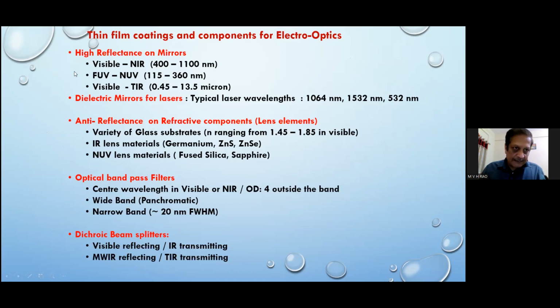A variety of optical films are made: high reflectance coatings on mirrors, and dielectric mirrors for lasers, for different types, 1064, 1532. These are lasers. Anti-reflection coatings on the lens elements, as I already told, all camera lenses should have an anti-reflection coating, whether it is an IR imaging camera or night vision camera. In that case also we require anti-reflection coating, and generally germanium and zinc selenide materials are used for these camera lenses. So after the fabrication of these lenses, we need to put anti-reflection coatings. And in the case of NUV also, we can use fused silica or sapphire.